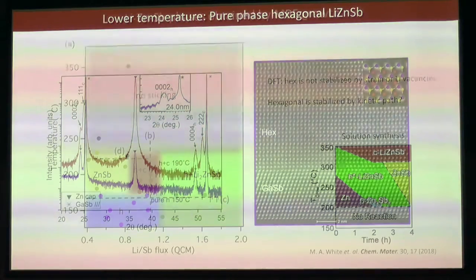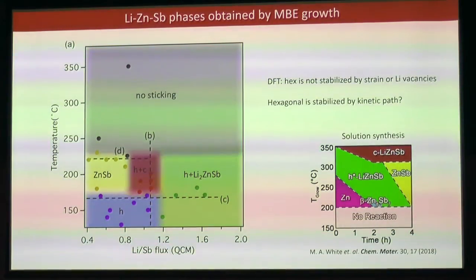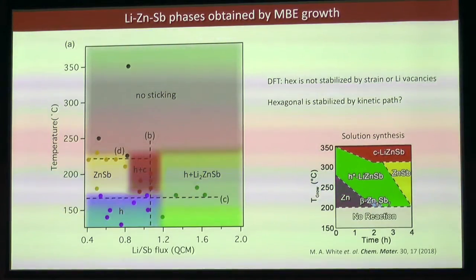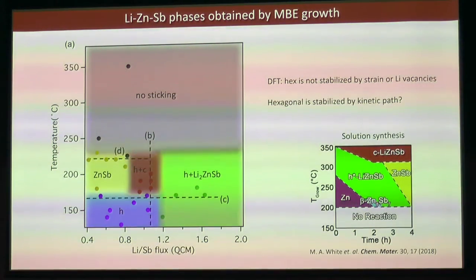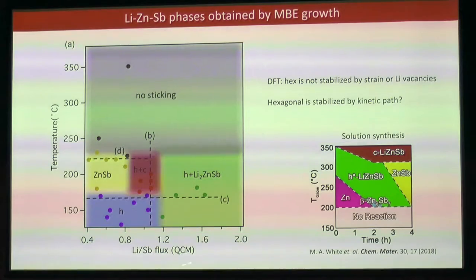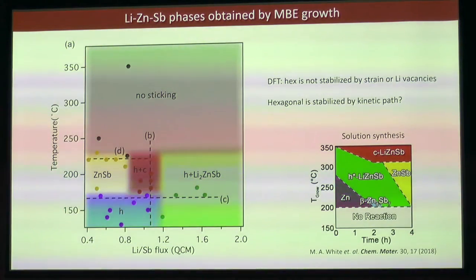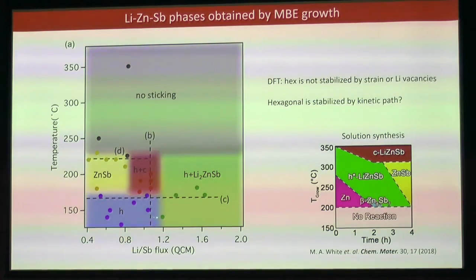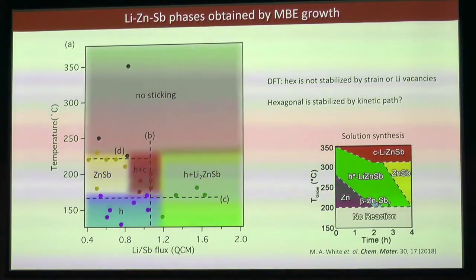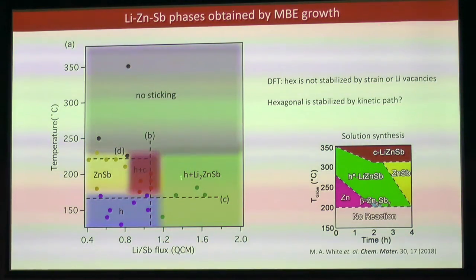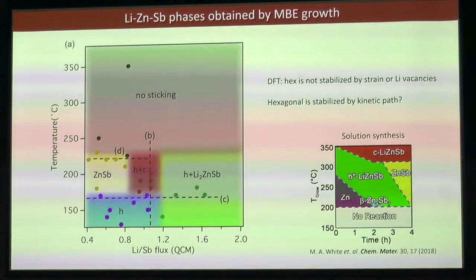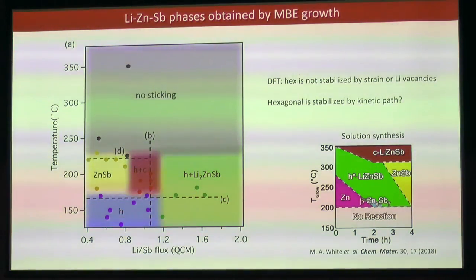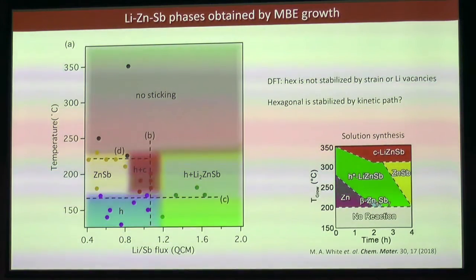Okay, so overall, these are the various phases that we observe during MBE growth of these compounds. As a function of growth temperature and lithium to antimony flux ratio, here's where we started, with this mix of hexagonal and cubic. We cooled down, grew at lower temperature, and can grow pure phase hexagonal. If you grow a little too lithium rich, you can precipitate out a cubic full Heusler phase, lithium 2 zinc antimony. Lithium deficient, you can form this layered zinc antimony phase.